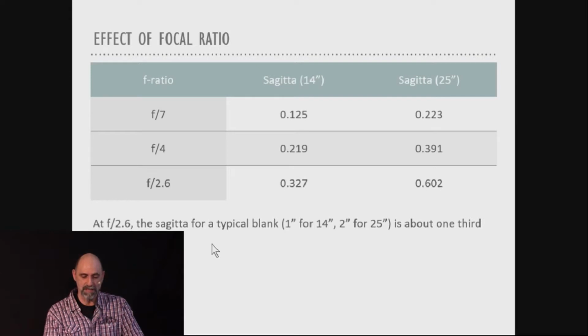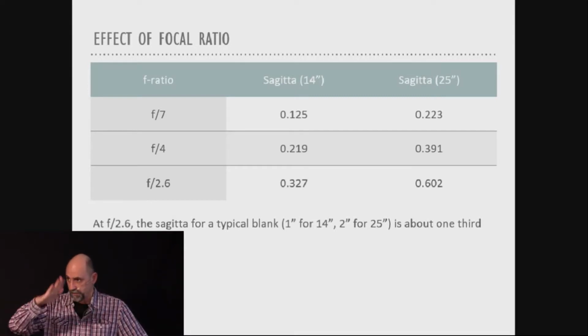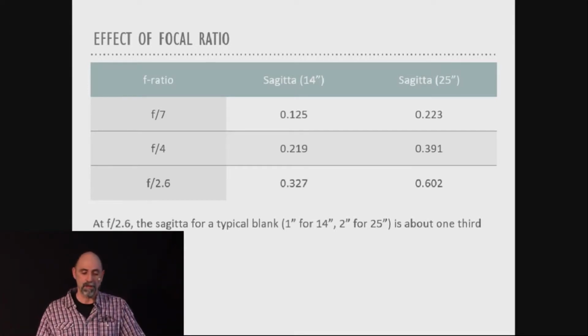So at f2.6, if your typical blank is going to be 1 inch for a 14-inch mirror or 2 inches for a 25-inch mirror, you're looking at about 1/3 of the thickness of your blank being carved away by the curve. What that means is that if you've got 100 pounds of glass and 1/3 of it in the center has been carved out, that leaves 2/3 there. It's going to totally mess up the thermal properties of that glass, as well as structurally. You're basically making it considerably weaker there. All of these things compound. So if you're looking at a large aperture, you can't actually fabricate a fast mirror without a whole bunch of other complications.